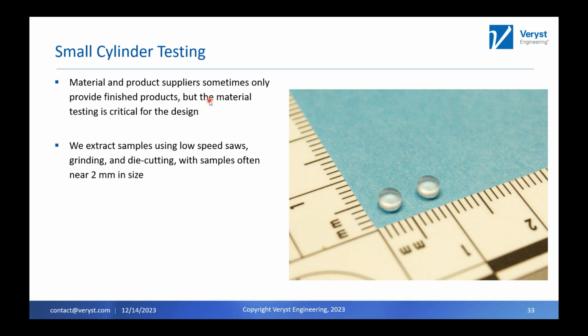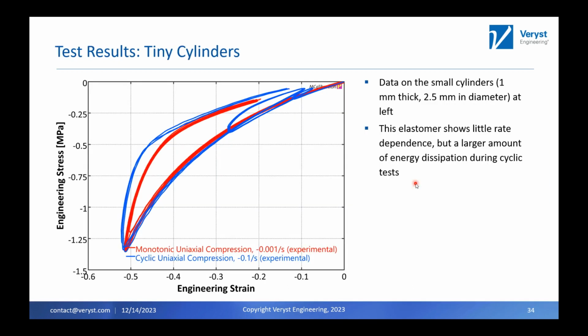And again, it was a complex shape, and we did some grinding, cutting, die cutting, low-speed saws to get these out and get cylinders. So these are near 2 millimeters in size. So you can see very small samples. They're very hard to work with and play with. But can we get good data out of these? Of course, if I'm showing it to you, the answer is going to be yes.